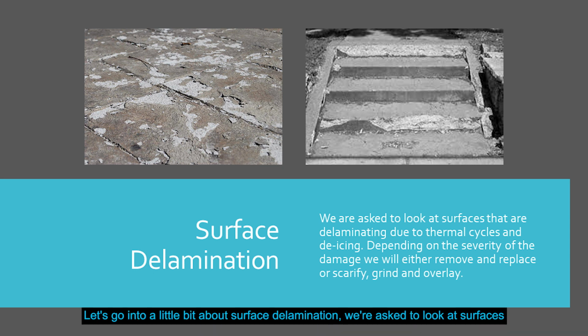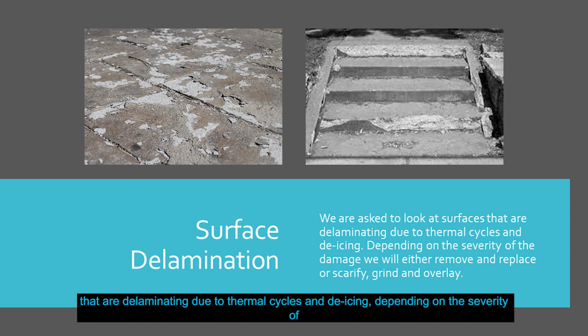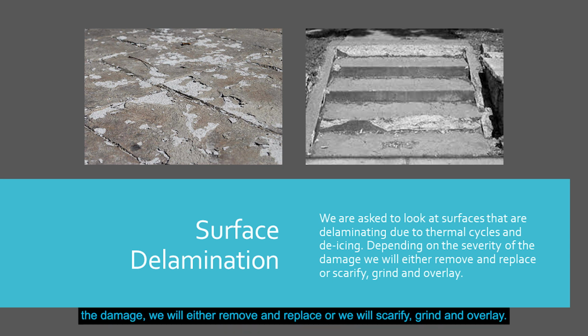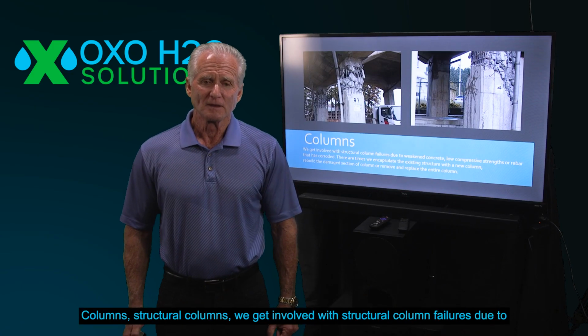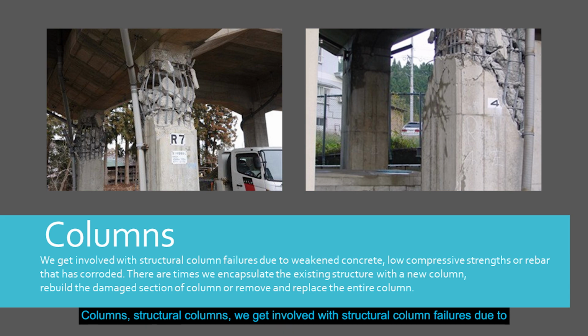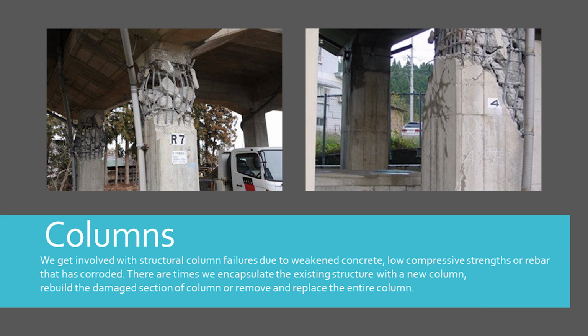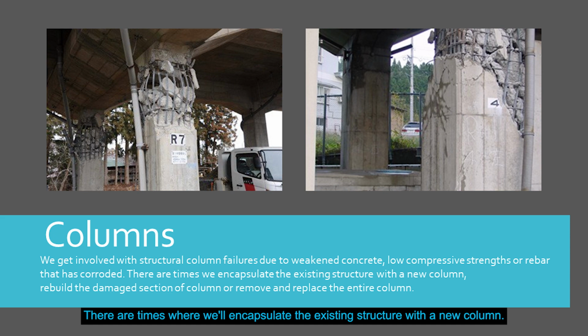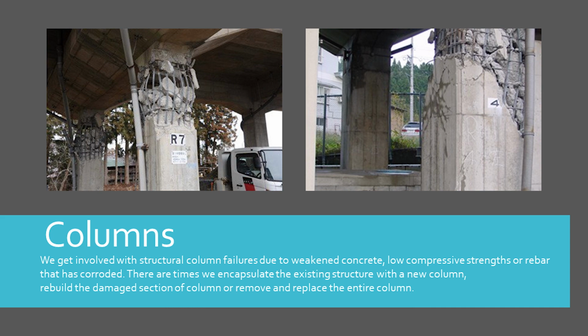Let's go into a little bit about surface delamination. We're asked to look at surfaces that are delaminating due to thermal cycles and de-icing. Depending on the severity of the damage, we will either remove and replace, or we will scarify, grind, and overlay. Columns, structural columns. We get involved with structural column failures due to weakened concrete, low compressive strengths, or rebar that's corroded. There are times where we'll encapsulate the existing structure with a new column. We'll rebuild the damaged section of the column, or we'll remove and replace the entire column.